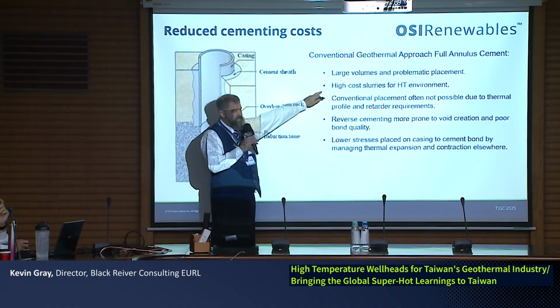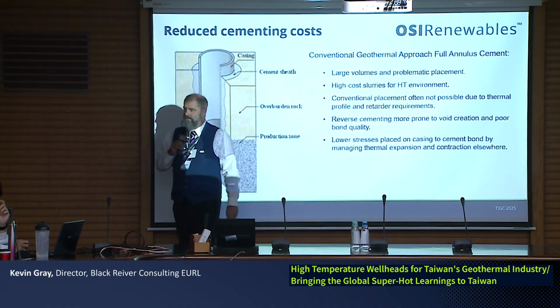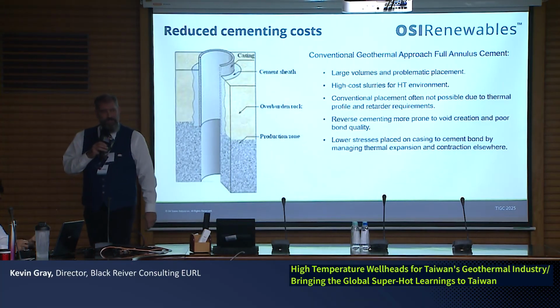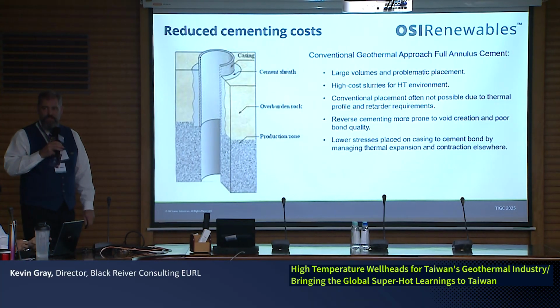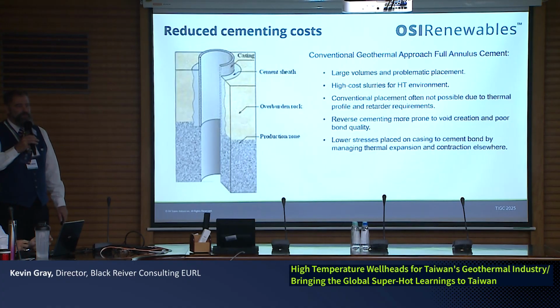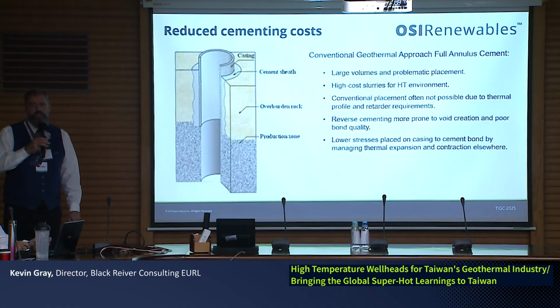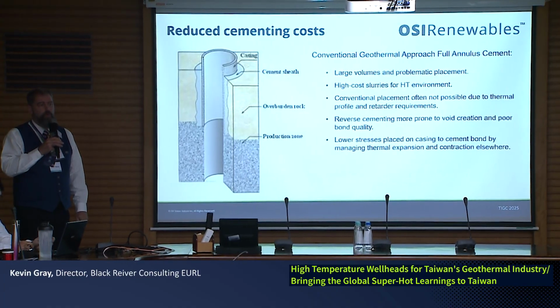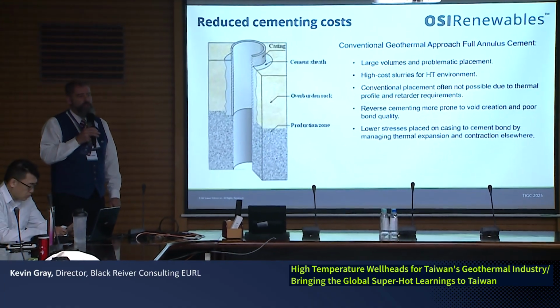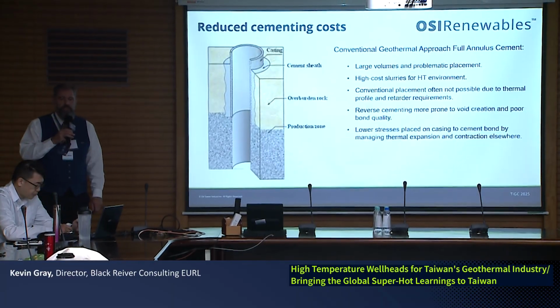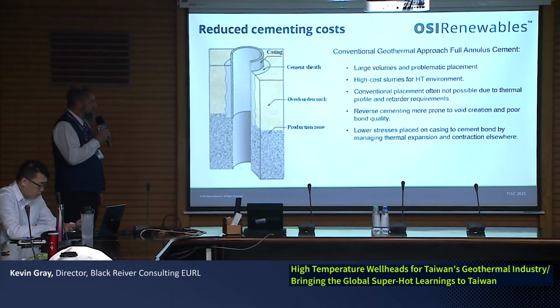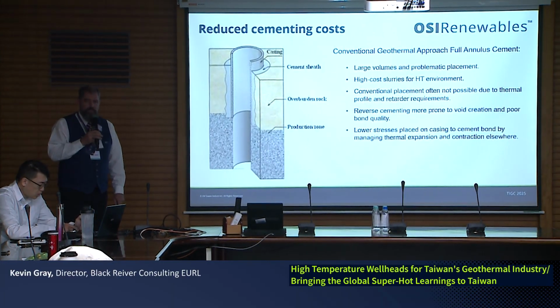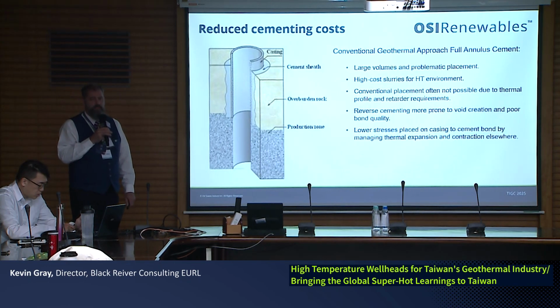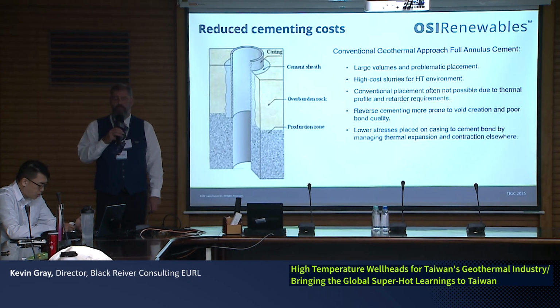The other thing is, with all deference to my colleagues in the cementing industry, when you ask for a high temperature slurry, the bill that comes with it is also high. And justifiably so, because these slurries are not ordinary Portland cement. They've put a lot of research and development into the development of high temperature slurries. And I believe that we are reasonably safe now with slurry design up to about 400 degrees centigrade.